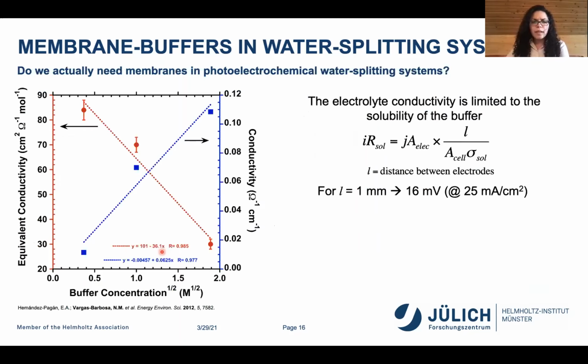And so we started to think about buffers, and if we think about doing water splitting in a buffered electrolyte, let's say with phosphate buffer, okay? And then we have an anode and a cathode where we want to collect oxygen and hydrogen. Do we actually need a membrane to separate the anode and cathode compartments so that we can collect the gases? And so we looked at things like, this is not particularly new, right? As buffer concentration increases, the conductivity of the solution increases, and the conductivity plateaus and is limited by the solubility of the buffer. This is not particularly new.